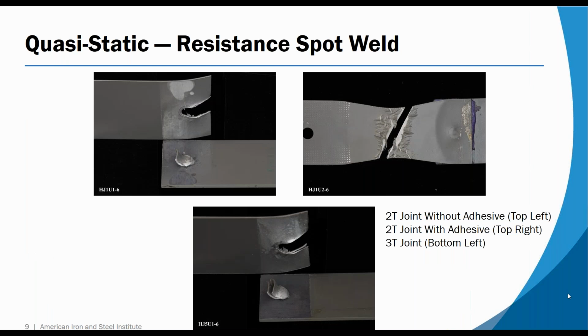Here are some selections from our baseline joints. In each case, for all of our 6 joints, we constructed resistance spot weld baselines and used them to set our performance goals. In the upper left-hand corner, you will see a 2 thickness joint without any kind of sealer or adhesive, and that's a pretty classic spot weld nugget that you can see.